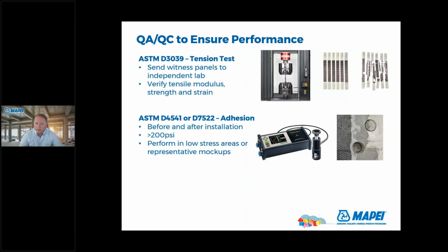A more important test is a bond test. And there's a couple of ASTMs for this. These are ASTM D4541 and ASTM D7522. They both work. D7522 is a little bit more geared toward FRP applications, where D4541 is more general coating type applications. But you're going to want to make sure that you have above 200 psi. If you have above 200 psi when you're pulling that off, you pass. And this is done before the application of FRP and then also after the application.